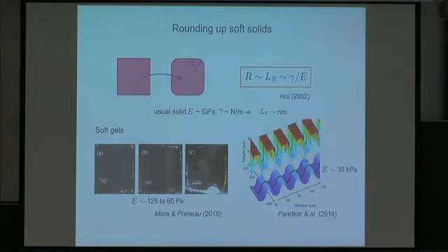How do you find this radius of curvature? Basically you balance the surface tension, the Laplace pressure that I defined before, with the Young modulus, which is also a kind of pressure, and you end up with a length scale, which I will call the stretching length scale maybe, which is the surface tension of the solid versus air, divided by the Young modulus of the solid.